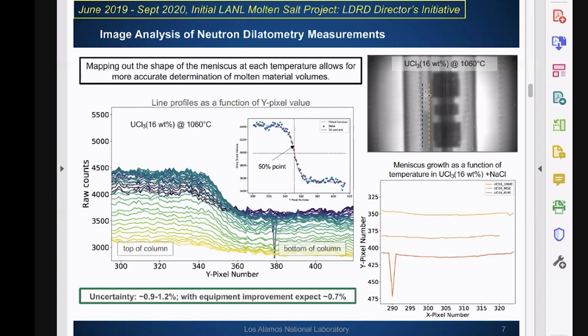And then if you follow the teal colored line, which goes down the center, crosses over the meniscus, you see a bigger change in contrast. So it goes from here to here. What this analysis does is it looks at the change in grayscale across that meniscus and across the X direction. It allows precise mapping of the meniscus location in both X and Y, and then we integrate over 2 pi, and that gives us precise sample volume. I like to point out the bottom left here. So far, we've gotten an uncertainty down to about 0.9 to 1.2%. We have some planned equipment improvement, the detector, the camera, et cetera, and we expect to lower this down to 0.7%.